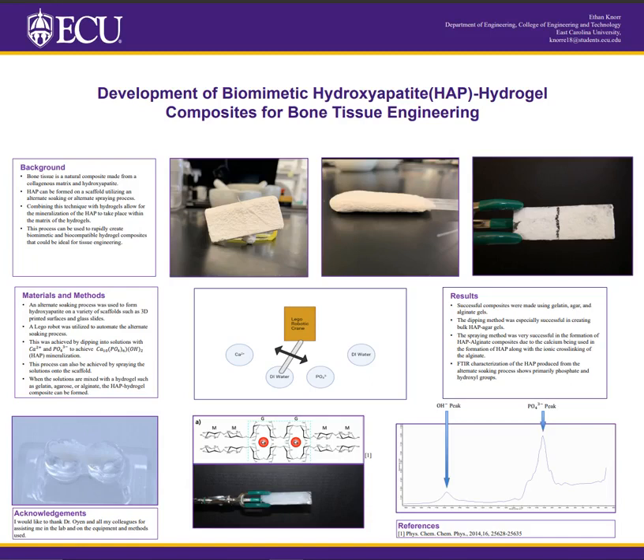The figures on the top row show 3 different composites developed on different scaffolds. The one on the left is a pure hydroxyapatite coating on a 3D printed scaffold. The one in the middle is an agar hydroxyapatite composite on a glass slide, and the one on the right is an alginate hydroxyapatite composite on a glass slide. The left 2 figures were made utilizing the alternate soaking process, and the alginate composite was made using the alternate spraying process.